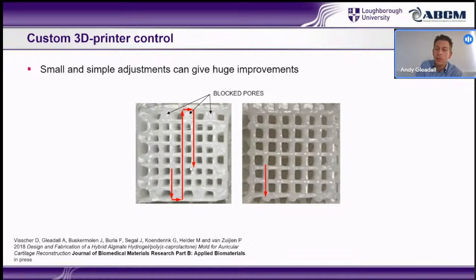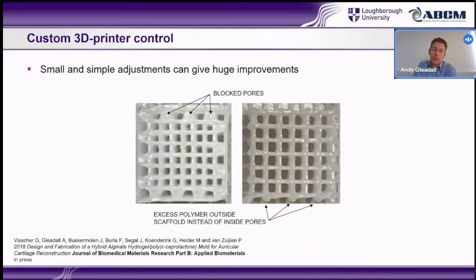Then a very simple adjustment, just telling the printer to move a little bit outside of the area before moving across, and then go up to the side and move a little bit outside before going across. That was all that was needed to shift these defects, which are kind of unavoidable for this system with this very flexible material. We couldn't accurately control the flow in such a way to print it perfectly. So we shifted the defects from inside the pores to outside the structures, where it made no difference at all for what we were researching. It's very, very simple, but it can make a massive difference to the quality of the research being conducted.